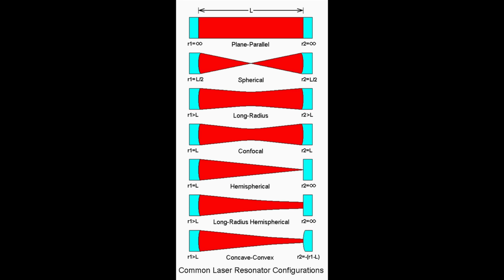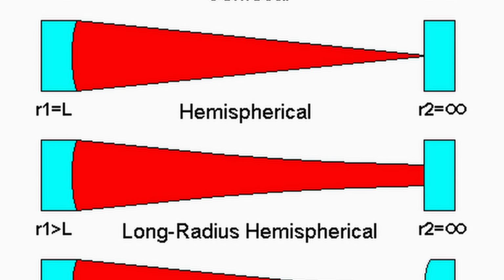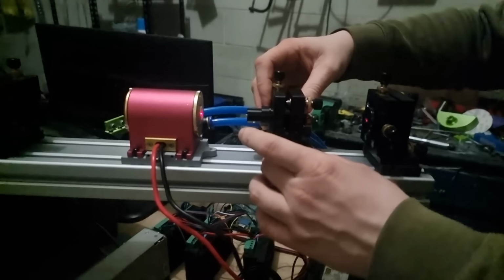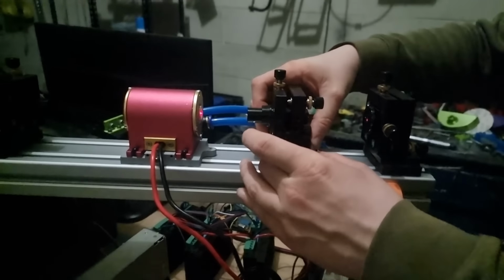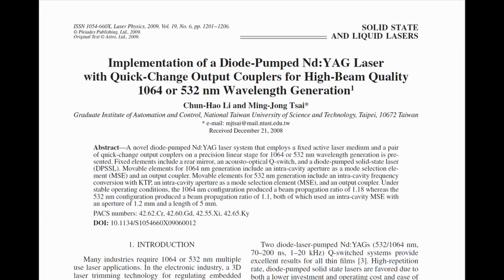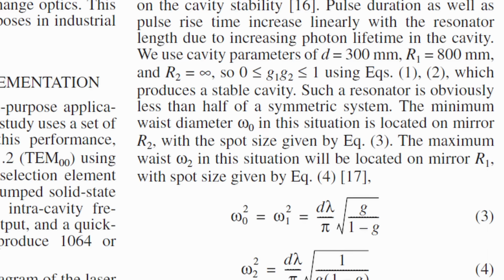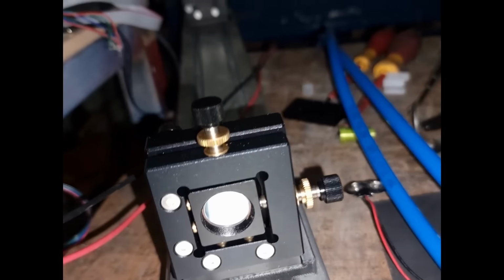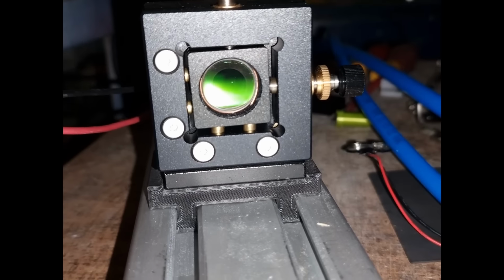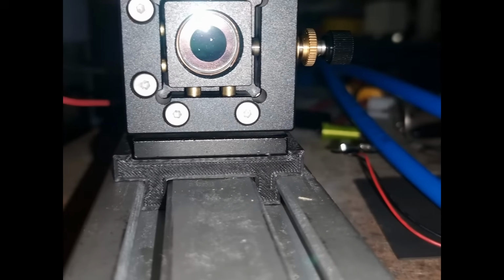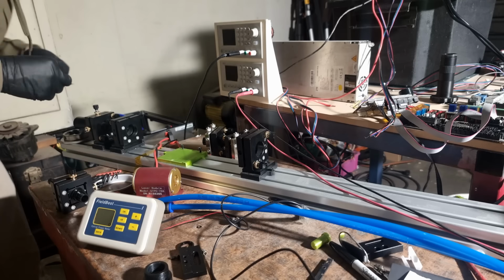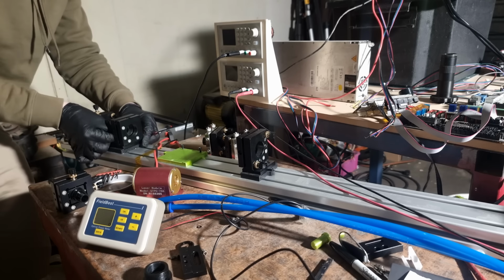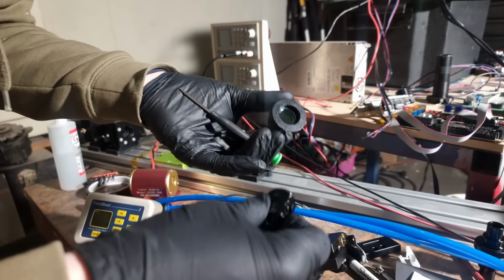I would opt for a hemispherical resonator as this is the most commonly adopted format for the lasers in this power band. In terms of spacing and what mirrors to use, initially I couldn't find much in the way of worked examples, but I did eventually find this paper which noted the use of a high reflectance mirror with a radius of curvature of 800mm and a cavity length of 300mm. I would use this as the basis for my first configuration, but quickly discovered the limitations of the cheaper mirrors I had bought, damaging the mirrors at around 20 watts. The original mirror mounts I purchased came with a set of mirrors from a factory system, but unfortunately I had no idea of their specs.